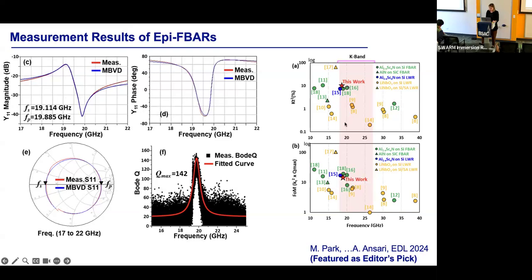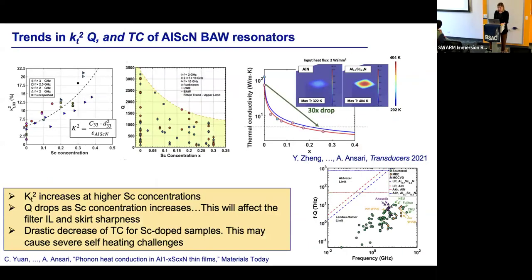So this is one of the highest, basically, FBAR devices made of aluminum nitride family in literature. However, as you can see, the quality factor is about 150, which could be better, and I'll try to explain what we've been looking into and how we can improve the Q above this number.